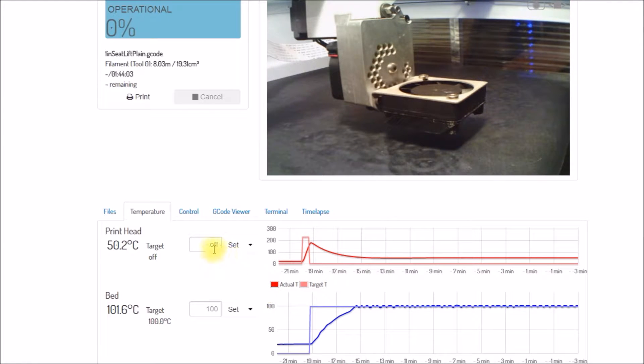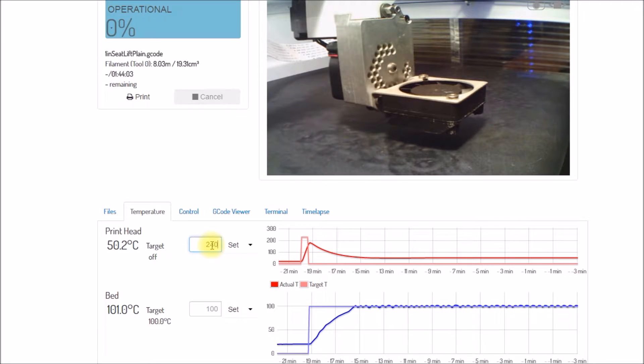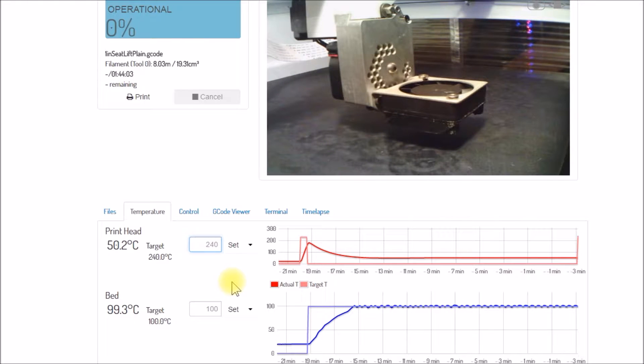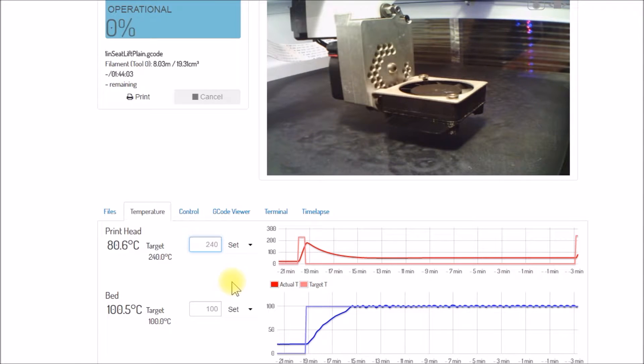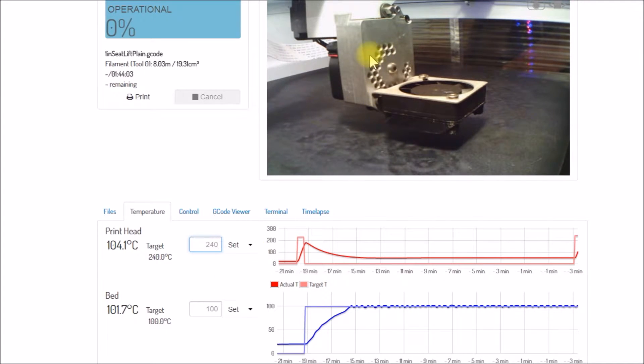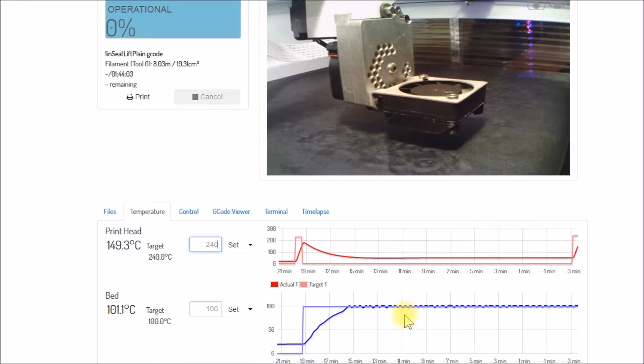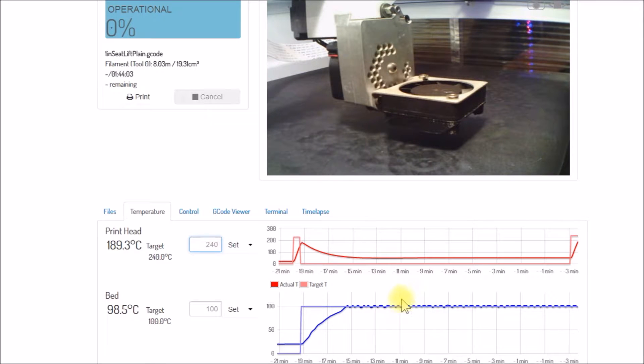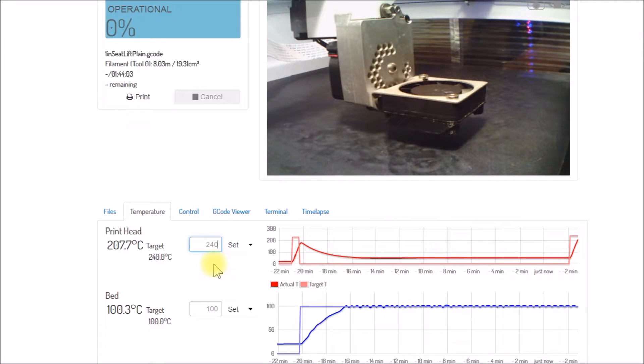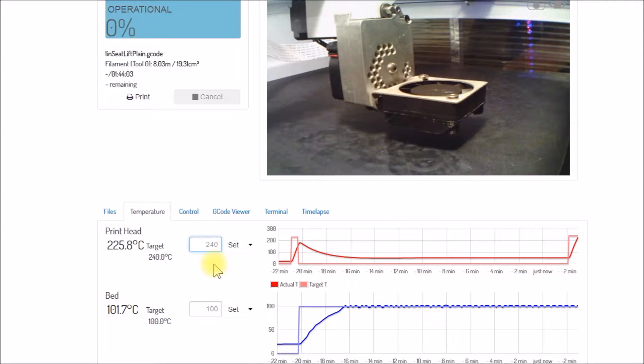I did put the front cover on, so I'm going to be printing ABS. I like to preheat the print head or extruder to the 240°C that I normally print at, and I find it's a little more repeatable if I give the printer a minute or two to get up to temperature. That way all of this aluminum here can get hot. So I give the bed roughly 10 minutes to heat up, and that heats up the build chamber with the front enclosure on. Then I let the print head come up to temperature, and I'll usually give it about a minute to warm up there.